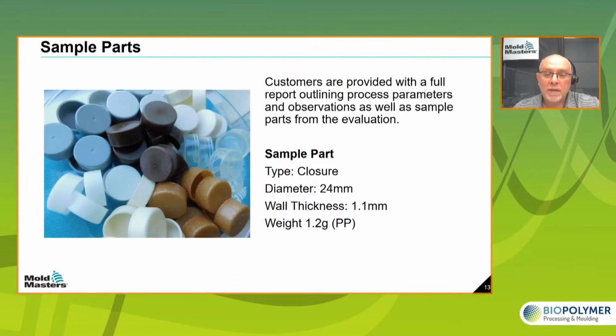So within our testing process, we run a variety of materials provided by our customer. We provide a full report on the performance. We provide samples. We can provide photographs of the parts. And in this case, we're looking at a closure, 24 millimeter diameter. It's quite a thick wall for a closure, 1.1 millimeters, and molding polypropylene, this part is approximately 1.2 grams.